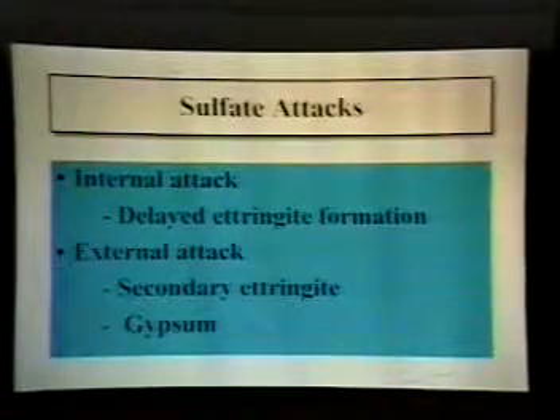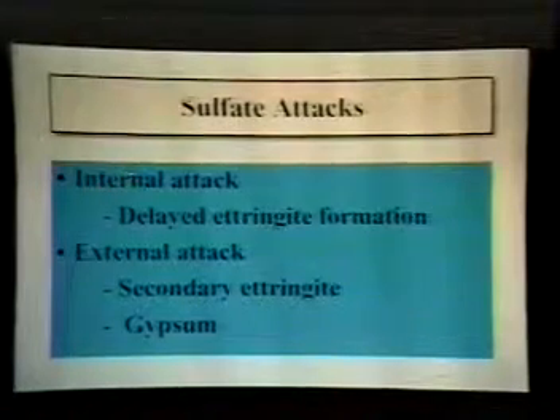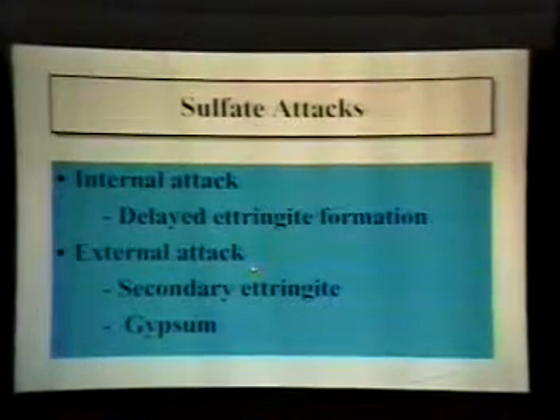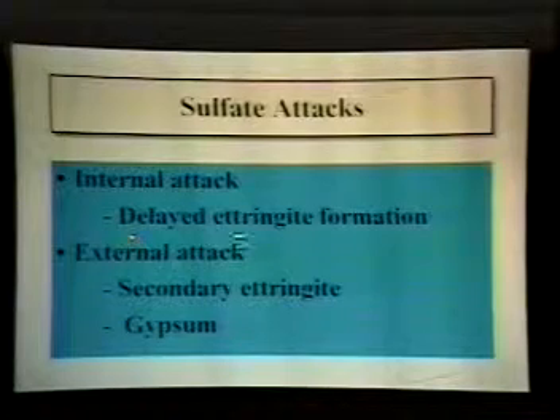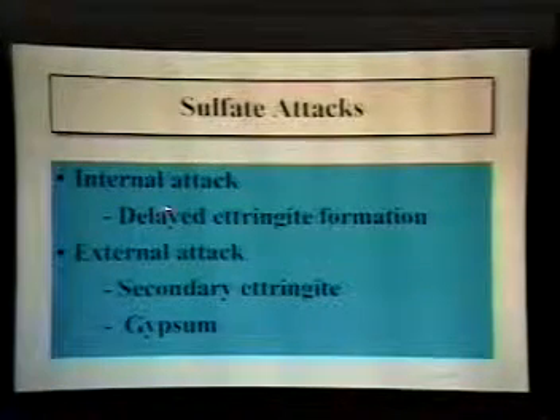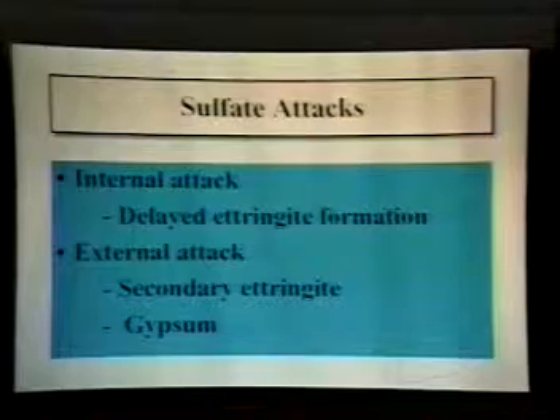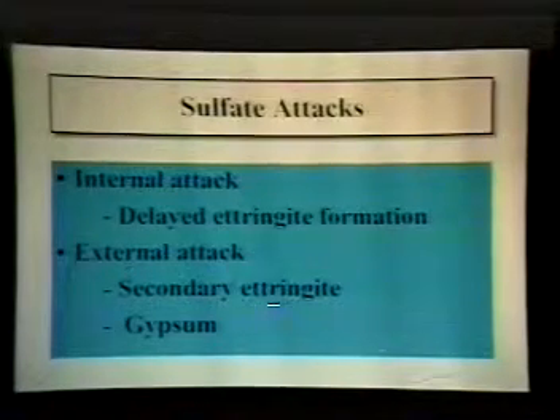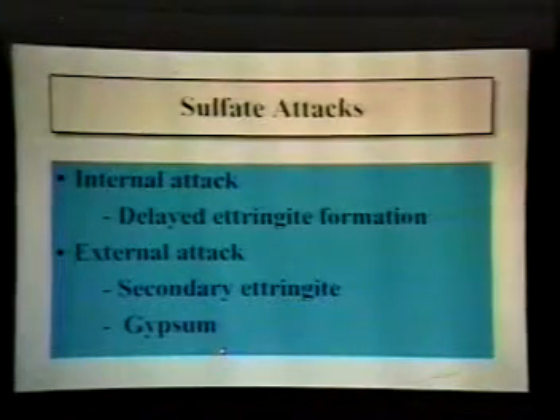Sulfate attacks. Two types. Again, I tend to divide into internal attack or external sulfate attack. Internal attack is a buzzword nowadays, delayed ettringite formation. External sulfate attack could be secondary ettringite or could be gypsum. This is a case of an external concrete which has been attacked by sulfate. And you can see all the ettringite crystals in the voids. The concrete has virtually decomposed and is filled with ettringite in the surface.